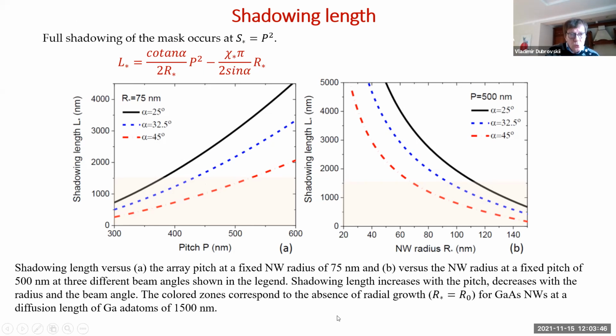And if, for example, I assume that in the case of gold catalyzed gallium arsenide nanowires, the diffusion length of gallium on the nanowire sidewalls is limited by incorporation. And now it can only be limited by incorporation because there is no desorption taken into account. So, and this was estimated at 1.5 micron in some works, or even there were works saying that it was more than 2 microns. So these shaded zones correspond to the regions in terms of pitch and initial nanowire radius, where there will be no radial growth at all. For instance, by decreasing the pitch, we can reach the regime where there is no radial growth for a given lambda, the diffusion length, or by increasing the alpha, or by increasing the radius.